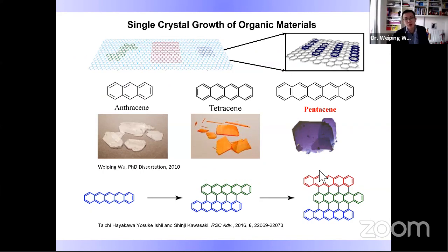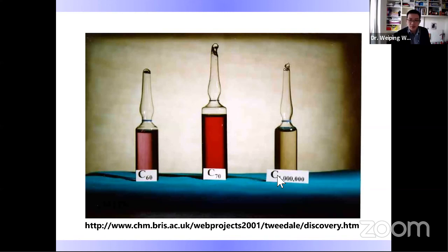Another piece of my work is growing single crystals of pi-conjugated molecules. I obtained very beautiful single crystals from arenes such as tetracene and pentacene. During my research, I also found some black spots in the pentacene single crystal, which were thermally converted into some graphene-like structure. When I think about the links between these organic molecules and carbon materials, we can see from these slides, which I found on the Bristol University Chemistry Department web page, that C60, fullerene, or C70, so-called carbon clusters, can all dissolve in these solvents.